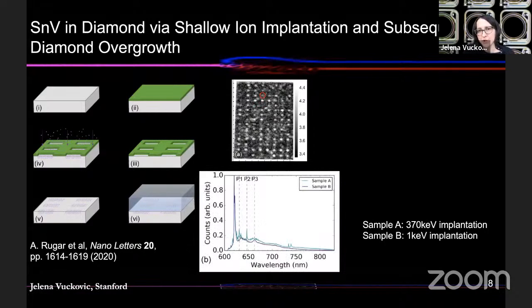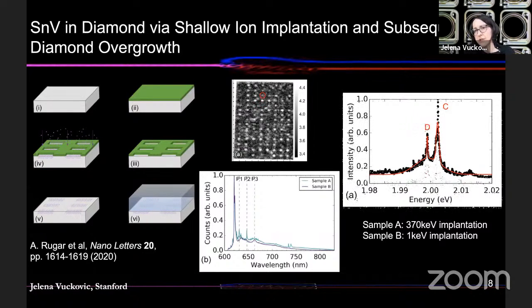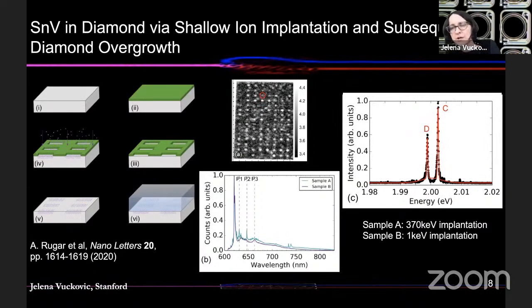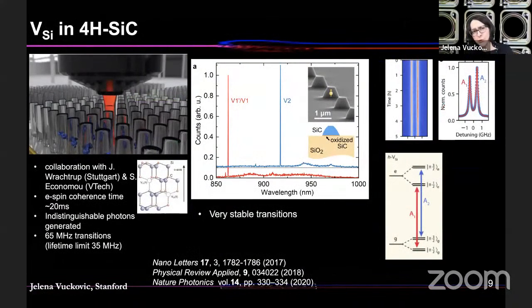Again, because of the reduction in lattice damage, you eliminate some spurious peaks that are occurring in the spectra that are not even related to tin vacancies. Also, line widths of the transitions are much narrower and comparable to naturally occurring tin atoms inside of the diamond lattice. So you are getting closer to the best experiments and best line widths that are measured that way. We also work with silicon vacancy in silicon carbide, the 4H polytype of silicon carbide.